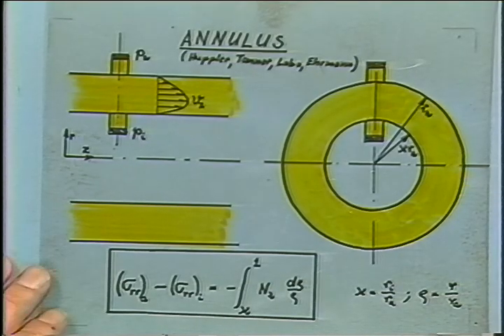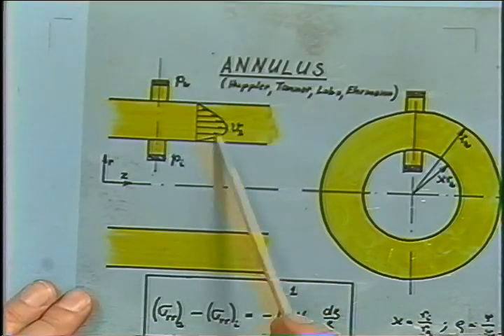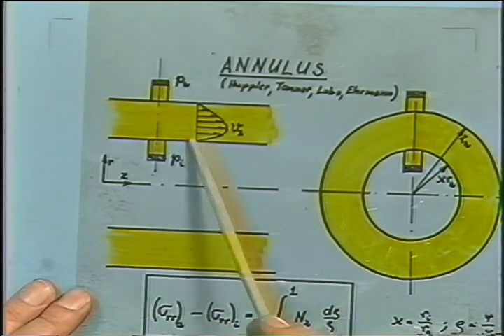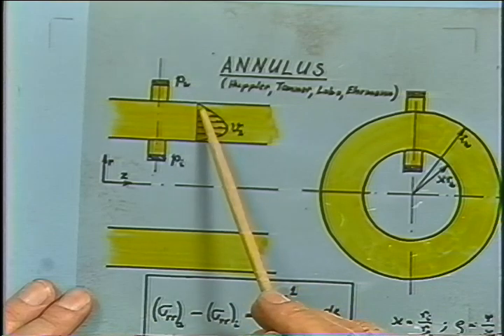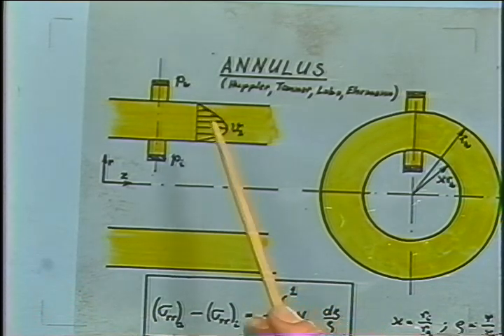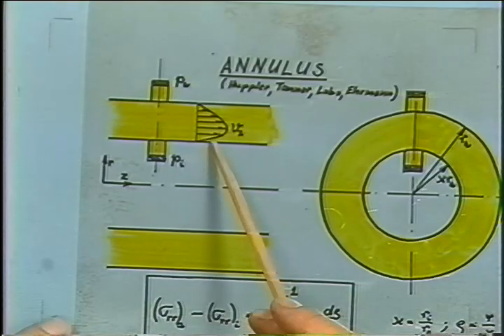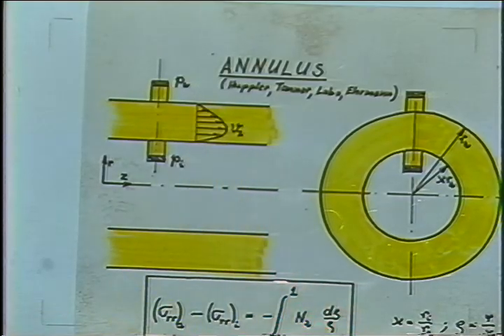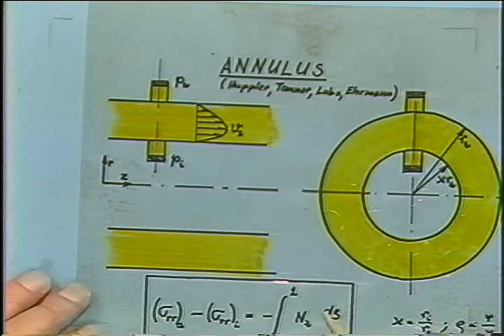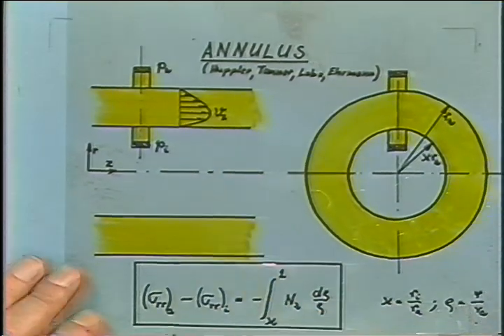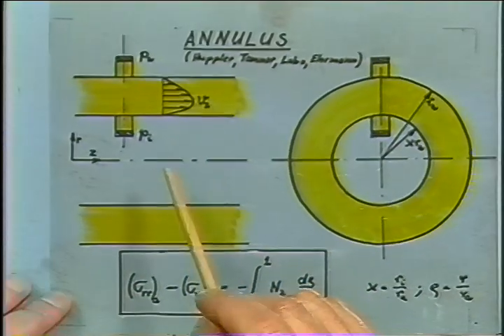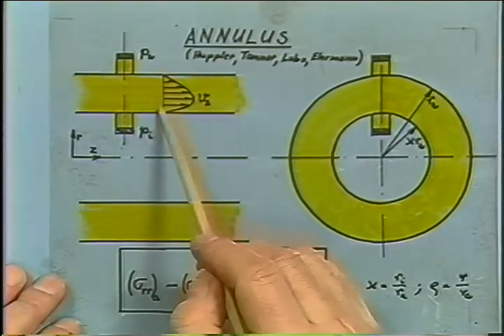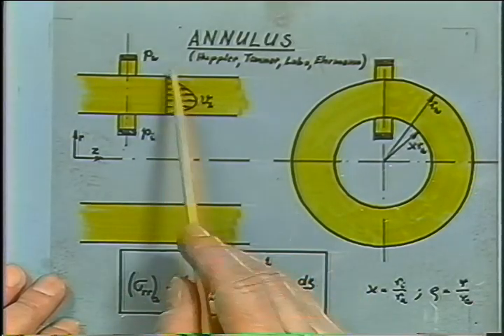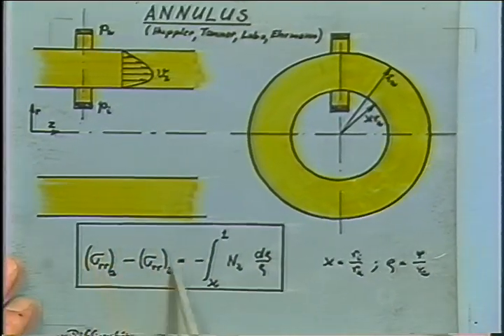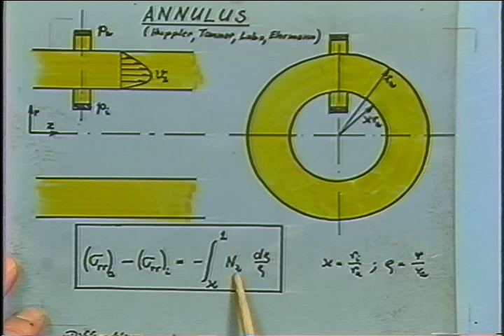But if we would use an annulus where the velocity distribution is somewhat asymmetric, so that the shear rate is different at the inner wall than at the outer wall, and of course that shear rate gives rise to normal stresses in that system, and the normal stresses are different at the inner wall and the outer wall because of that asymmetry in that flow field. So we can write the momentum balance for that type of flow and calculate the pressure difference between inside and outside, or the normal stress difference in radial direction on the inner wall and the outer wall, which is basically this here, and that's given by the second normal stress difference.